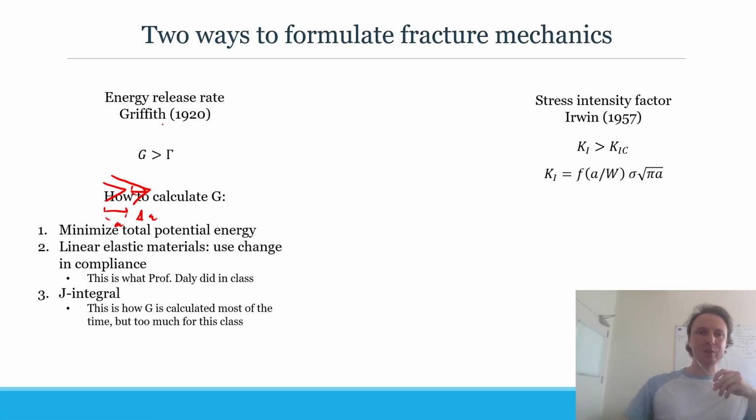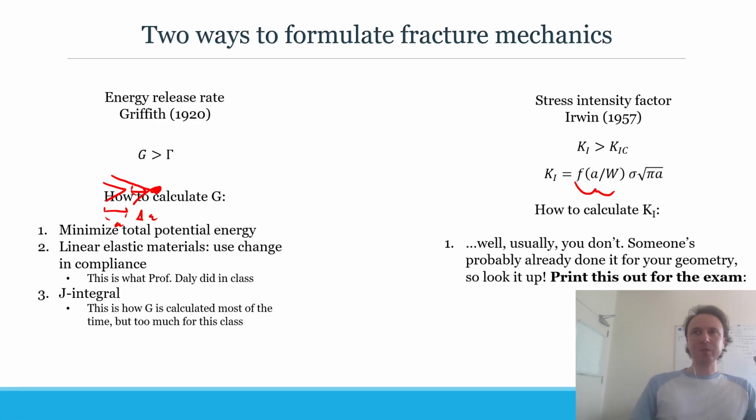basically if you integrate around far from the crack tip, you can get the energy release rate, and it's always elastic far from the crack tip. And of course, that's not ideal in some situations because we really only care about the intensity right here at the crack tip. So that's the idea of the stress intensity factor. Rather than having all of this material dependence where we have to worry about whether it's elastic or not, we just have this geometric dependence right here on this factor F. And so you don't normally calculate F, you just get it from the table.